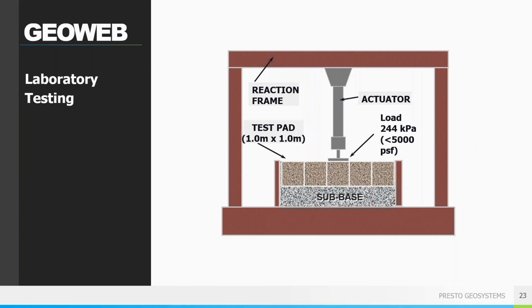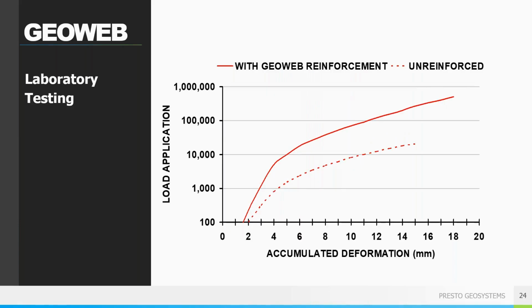So since the previous testing was under static loads, we also went ahead and did a dynamic load test. Here the pavement load testing compared unreinforced and reinforced materials over the same subgrade. Deflection of 0.6 of an inch is assumed to lead to failure of the pavement system. Therefore, we applied the load repeatedly until that 0.6 of an inch of accumulated deformation occurred.